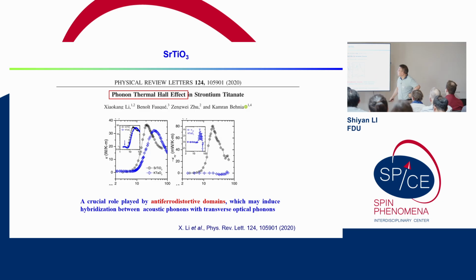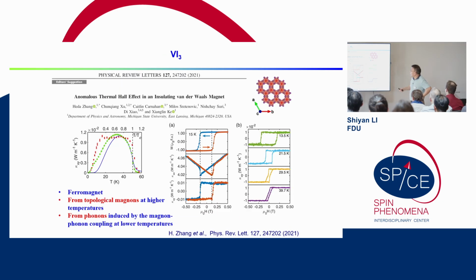Okay, and interesting, a group from Michigan State University measured this two-dimensional ferromagnet. They found that the thermal Hall signal comes up immediately below this magnetic transition. It is also pretty high at low temperature. At high temperature, they attributed it to the topological magnon, but at low temperature they attributed it to phonons induced by the magnon-phonon coupling.